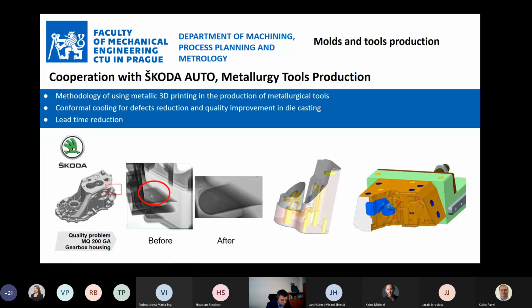The other application is conformal cooling. That means trying to do better cooling channels in the molds, whether it's for aluminum casting, for example, high pressure die casting, or for injection molding when you are working with polymers. So conformal cooling basically helps you to solve some problems. This was the original, for example, porosity or lunker within the gearbox housing. And you can see that you can prevent these non-conformities when you can cool this specific place faster than the rest of the material, then this will not occur at all. So this was basically one of the first steps in cooperation with Škoda Auto on this insert for basically a quarter of the mold.